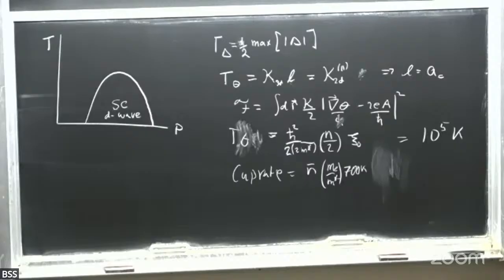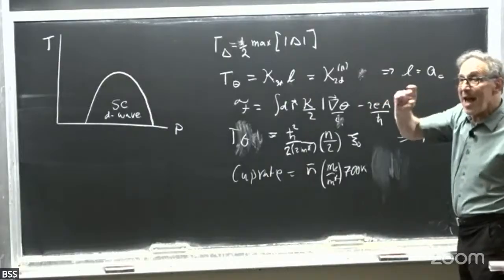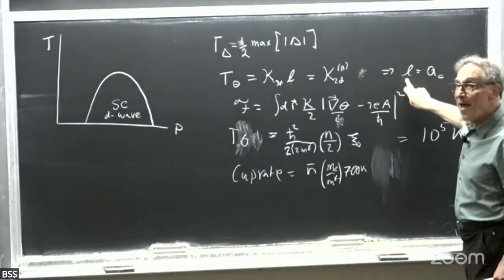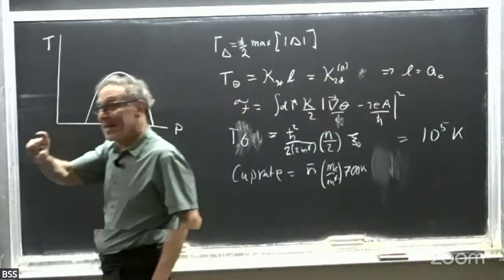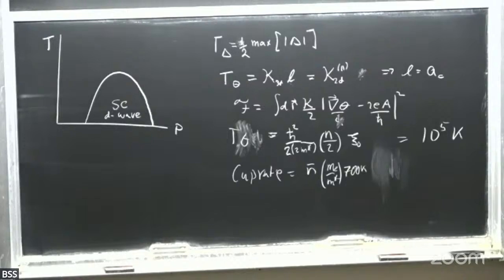Sorry, I mean, there are numbers for the Fermi energy in the cuprates. It depends on exactly how you extract it from experiment, but in lead, the Fermi energy is 10 eV, and in the cuprates, the Fermi energy is maybe half an eV. So there's already more than an order of magnitude. No, so the length scale here is the c-axis coherence length. So one factor comes from the fact that the length scale that comes in is also an atomic length scale, so that's the other big factor. Yeah. Okay.